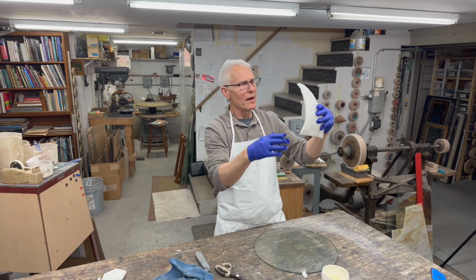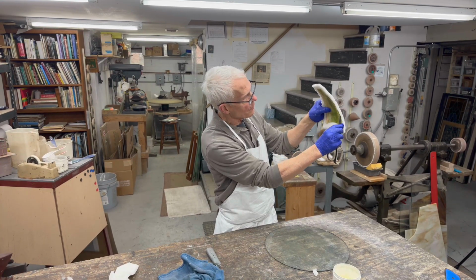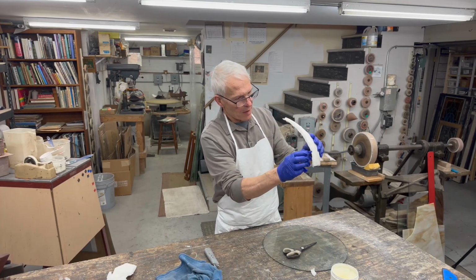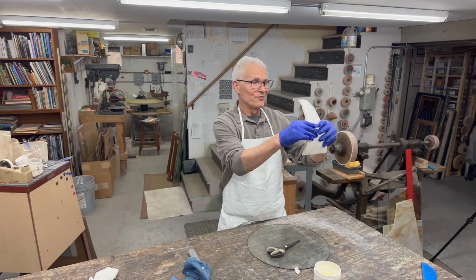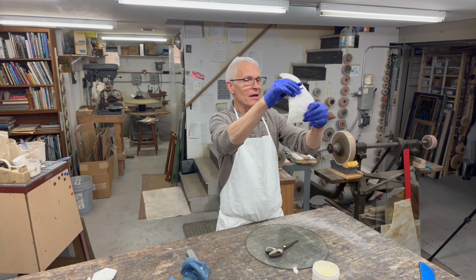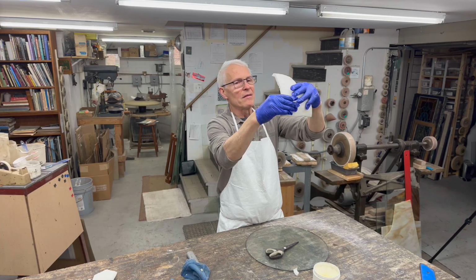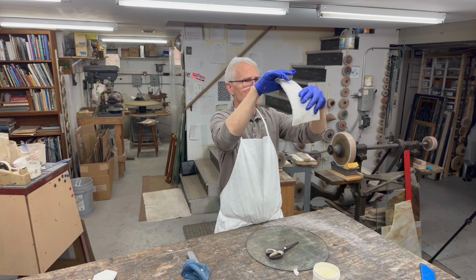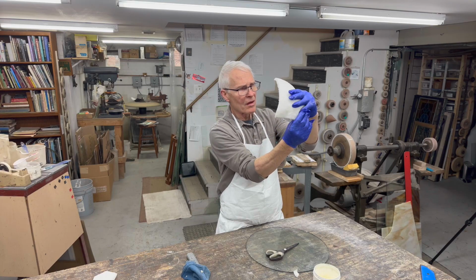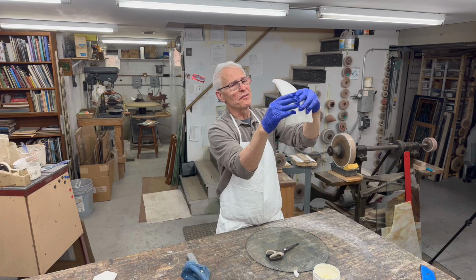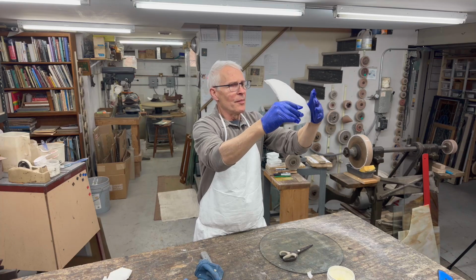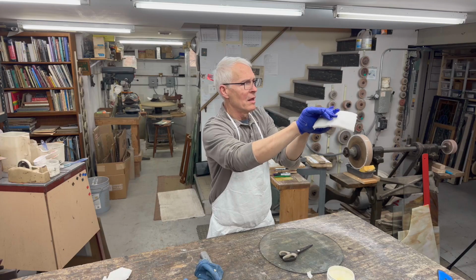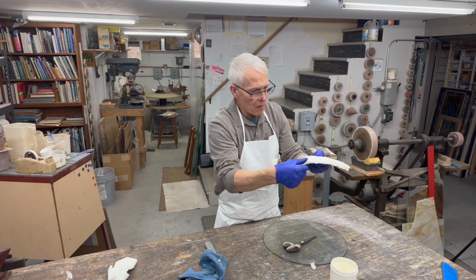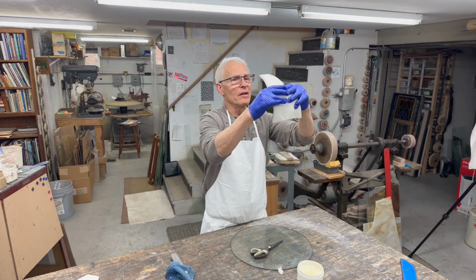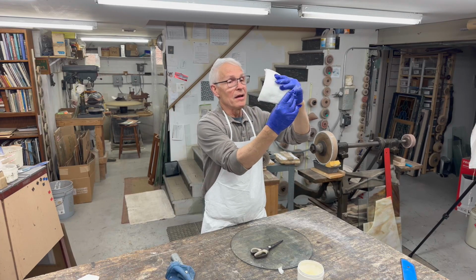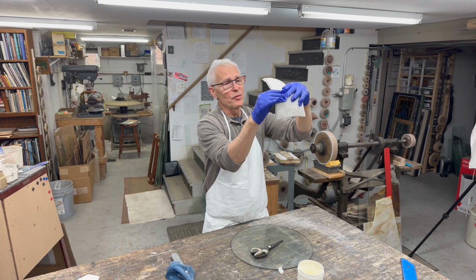Years ago, when I used to use more of this product, I would cut it really pretty close here and here, and I'd run some tape and tape it to the glass. That's one way of doing it, but for the most part, this product is great because it's a quick way to make a mold. It's more expensive than the powder mold or the plaster film mold that we'll go over later. Since it's wet, we'll have to set this up and put a fan on it. Believe it or not, it's going to take about a day for this to dry.